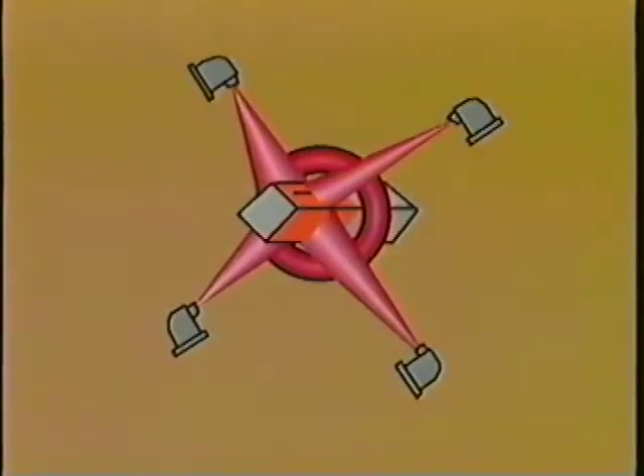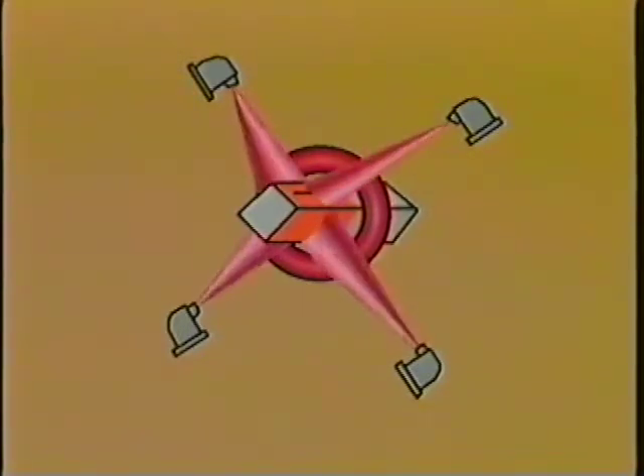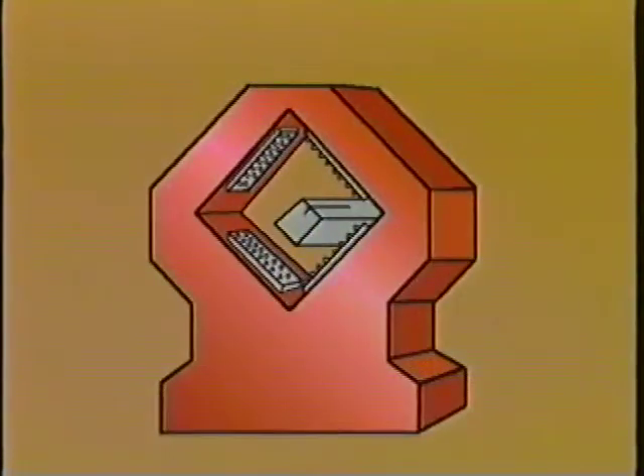By scanning the surface with heat-sensitive infrared detectors, the temperature profile can be recorded and passed on to microprocessors. Subsequent analysis of the data locates all the defects. This information is fed to a manifold with paint spray nozzles, which marks the defect locations on the billet.